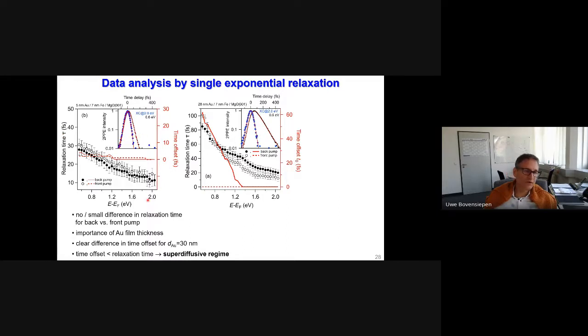which is basically this exponential decay. For the thin layer of gold, we cannot see this time offset being different from 0, but we can see some variation of the relaxation time here going from 2 electron volt to 0.7 electron volt above the Fermi level. For the thicker gold film, we see a very specific behavior of this time offset. It starts really to kick in very clearly at energies below 1.3 electron volt. If we do the backside pumping, for the front side pumping, we have no observation of such a temporal offset. And then you see already here that the relaxation times, these black data, are different compared to the thin gold layer. I will come back to this.